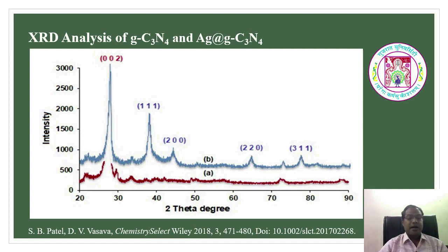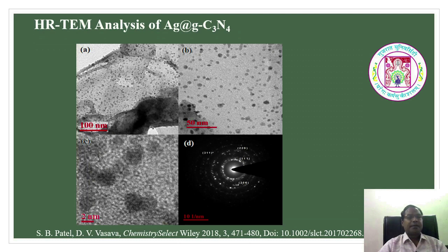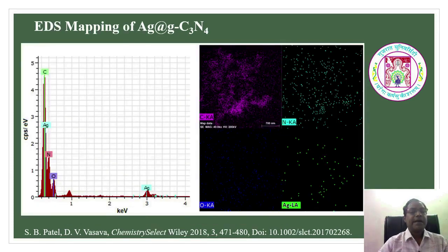So here it can be confirmed that the silver nanoparticles are crystalline in nature, and it also indicates that the size of the silver nanoparticles is calculated to be around 6 to 12 nanometers. The calculated particle size, that is 6 to 12 nanometers, is in good agreement with the HR-TEM analysis of the silver nanoparticles. So here it indicates the size of the nanoparticles, and that can be confirmed by the HR-TEM analysis.